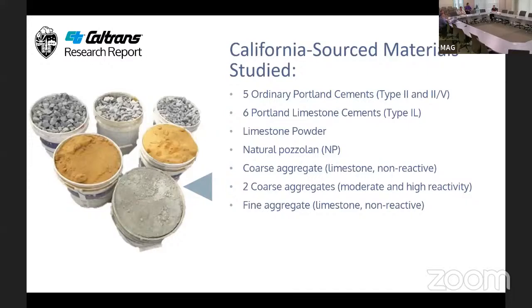All the cements for the Caltrans study were locally sourced out of California. They obtained 5 OPC cements, some type 2, some type 5, 6 PLC cements. I believe they had 2 different levels of limestone replacement, as well as a limestone powder and a natural pozzolan. And they additionally had both coarse and fine aggregates that were moderate and high reactivity and non-reactive. So the full gamut. And they did lots and lots of concrete and a lot of tests.